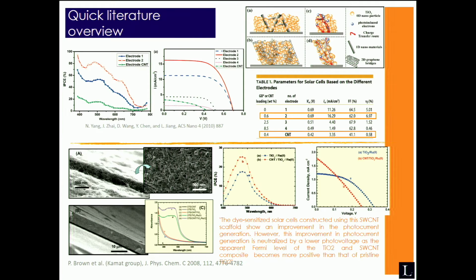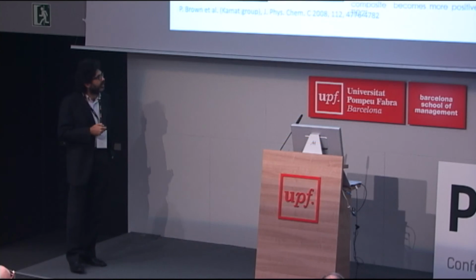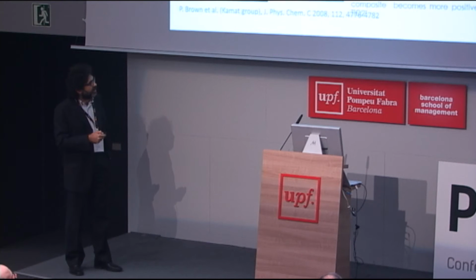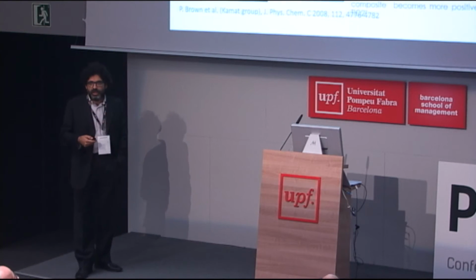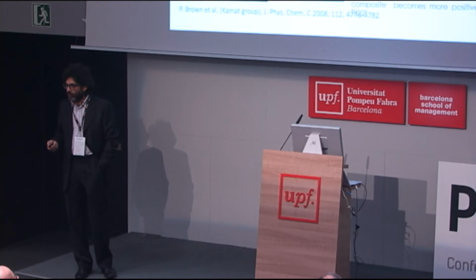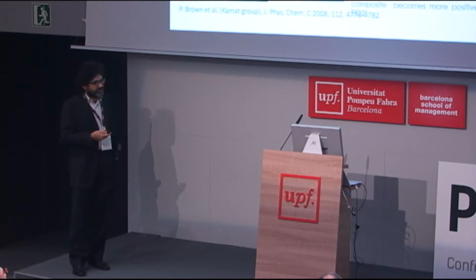The idea was preliminarily drafted in 2008 by Professor Kamat, and he was very negative about the outcomes of this system, because what he did, he took a forest of carbon nanotubes, covered it with titanium oxide nanoparticles, and then tried to test the solar cell. As you can see here, he got an increase in photocurrent density, but a significant decrease in open circuit photovoltage. So essentially, the photoconversion efficiency was not increased at all, and his conclusion was that the system doesn't work.